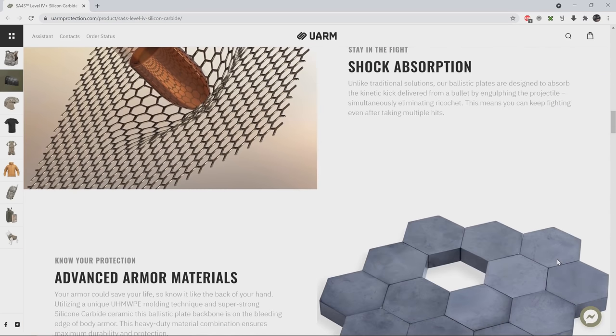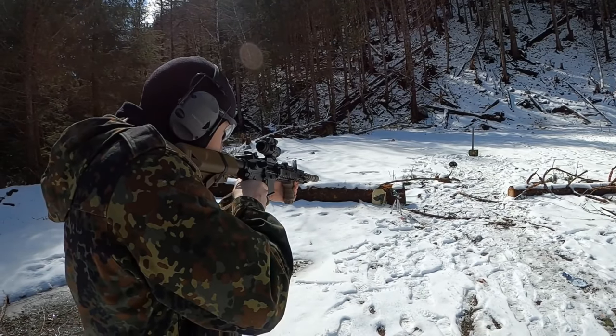Buffman, for example, thought these plates looked like the Ukrainian U-Arm plates. On the multi-hit durability side of things, I conducted a follow-up test of this plate versus the Army's new M855A1. We hit the same exact spot three times in a row, but the plate only stopped the first round. The round off to the right, however, was stopped. The next test was to get within a single hexagon length away from the initial impacts. That round, just one hexagon away, did not penetrate. The next upper hit, however, did penetrate. These results are pretty good for a ceramic plate, although I did notice some sparking from the slow motion, suggesting some limited splash effects. I found some jacket from the 5.56 rounds embedded in the carbon fiber — perhaps the thin layer of aramid is supposed to diminish that effect slightly.